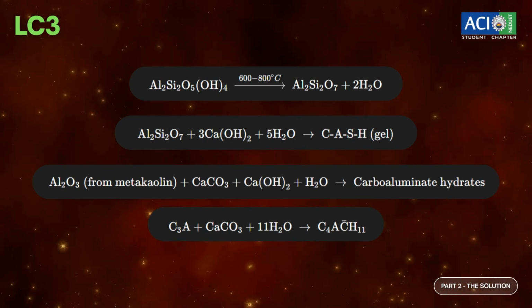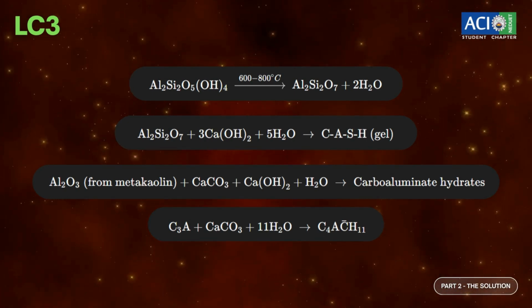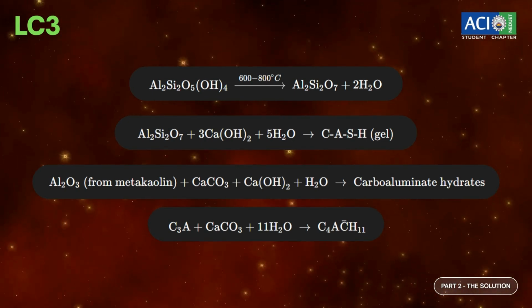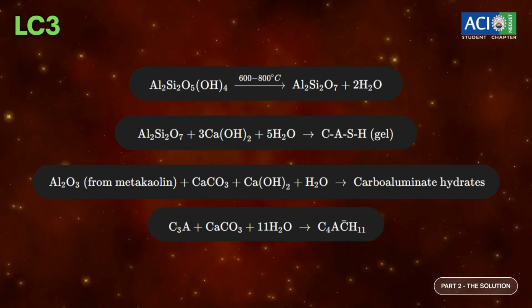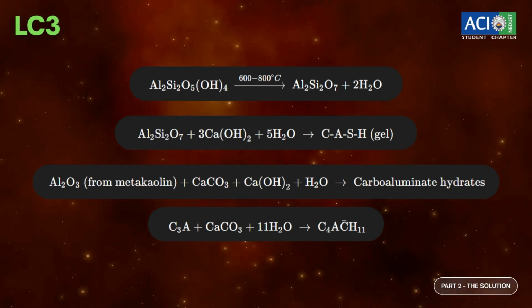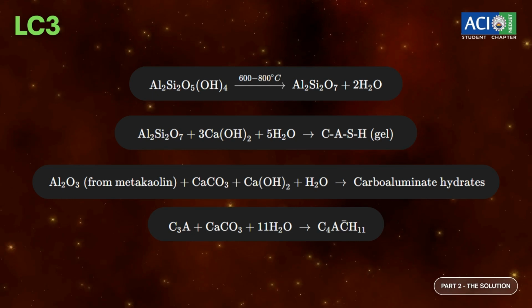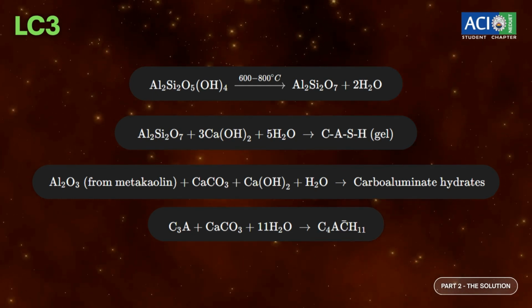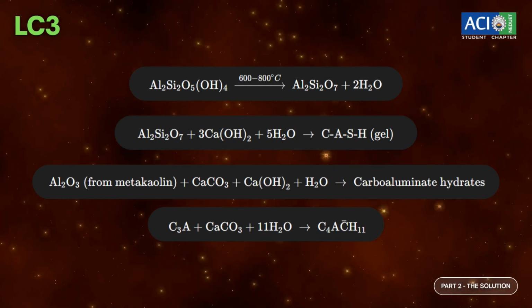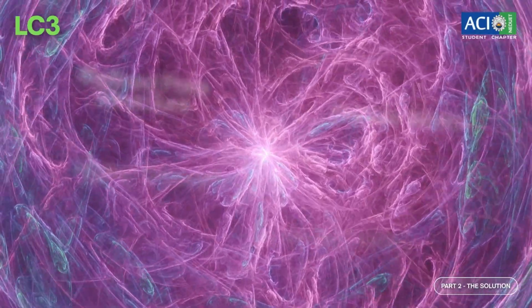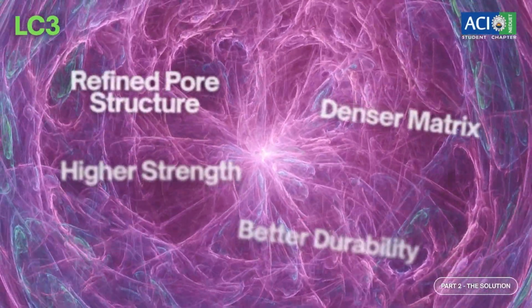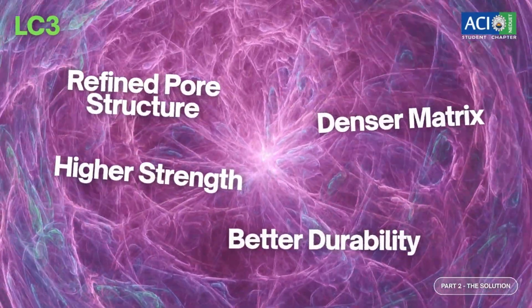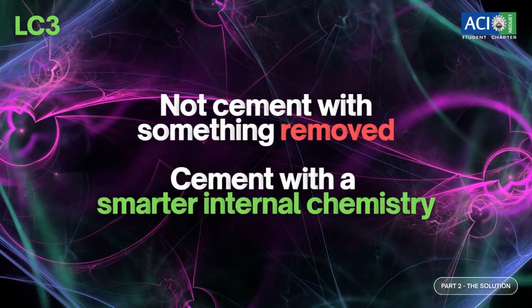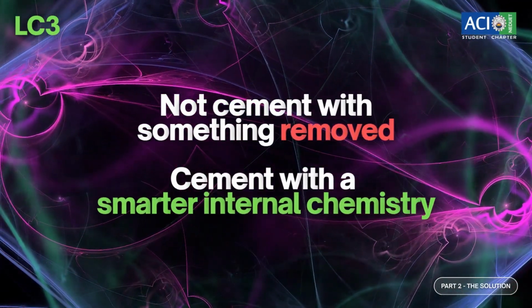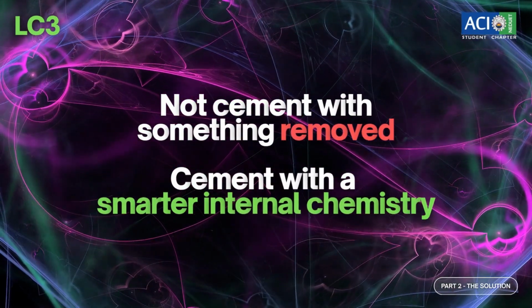Third, chemistry. When kaolinitic clay is calcined, it forms a reactive material often referred to as metakaolin. This reacts with calcium hydroxide like a pozzolan, but LC3 goes one step further. The alumina from the calcined clay also reacts with limestone to form carboaluminate hydrates, along with other hydration products. These reactions refine the pore structure, densify the matrix, and contribute to strength and durability. In other words, LC3 is not just cement with something removed. It is cement with a smarter internal chemistry.